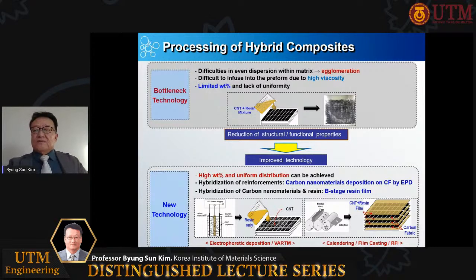By hybridization of the reinforcements, carbon nanomaterials, even deposition on carbon fabric by EPD may be processed. By hybridization of carbon nanomaterials and resin, B-stage resin film may be processed. In the bottom left view, the resin is added to a stack of carbon fabric with evenly deposited CNT before the hybrid composite processing. And in the right view, the resin film containing evenly distributed CNT by calendering is alternatively stacked with carbon fabric before processing with resin film infusion process.